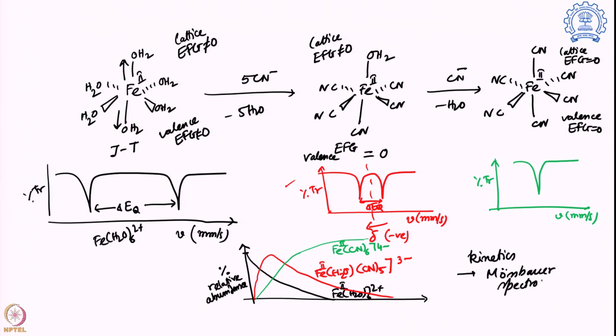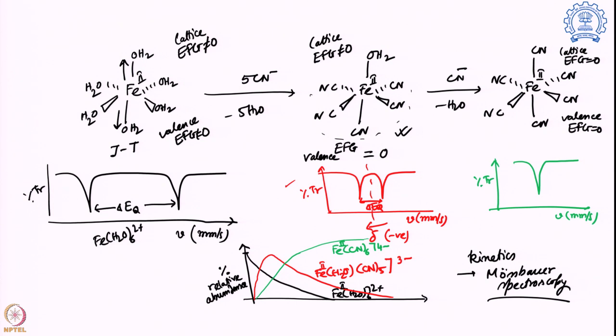And over there, one question might come to your mind: why am I seeing this molecule where 5 of them are already exchanged, why can I not see the 1, 2, 3, 4 cyanide exchange systems? Those are actually happening, but those reactions are happening at a much faster rate, even at 5 degrees centigrade, and it is happening before I can record a Mössbauer spectrum. So that is why I am only seeing this particular sample, one of the stable intermediates, and that is the first thing I am able to see. The previous ones, I cannot see. If I go to very low temperature, we might be able to capture those other intermediates also.